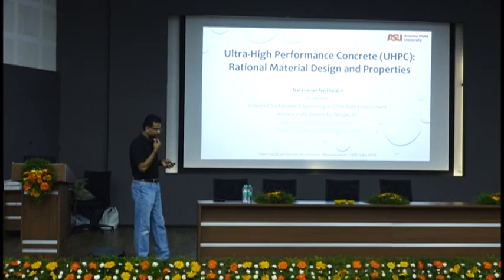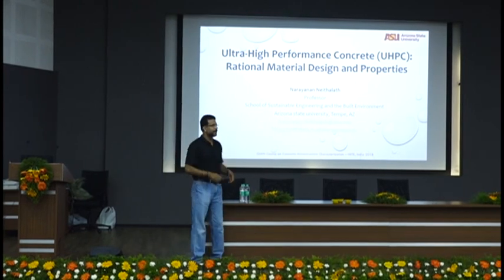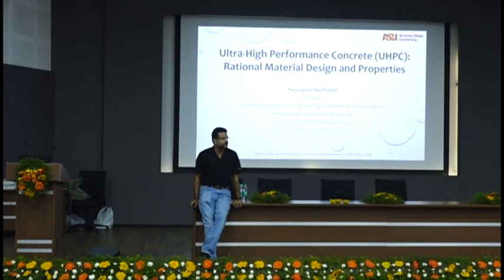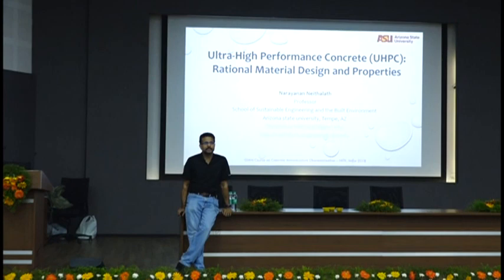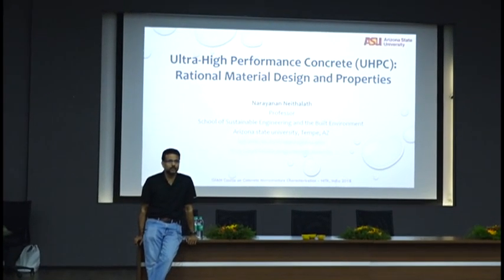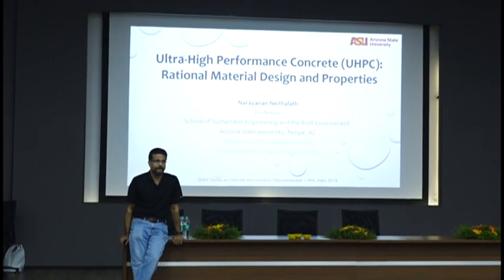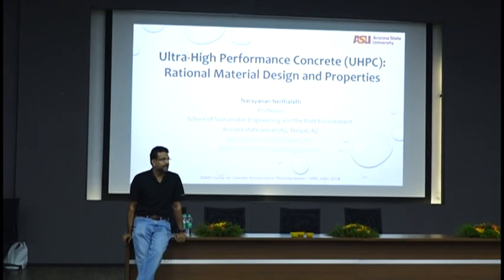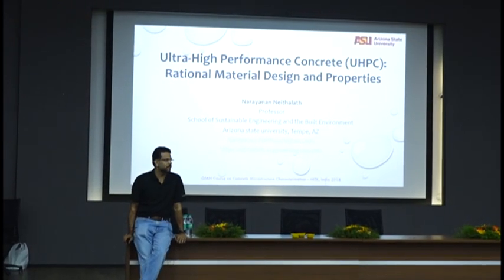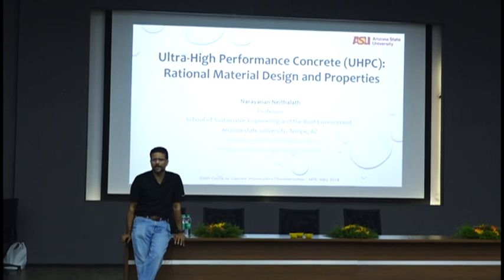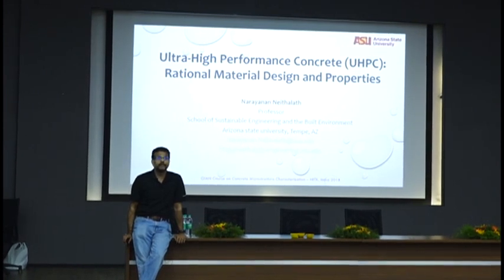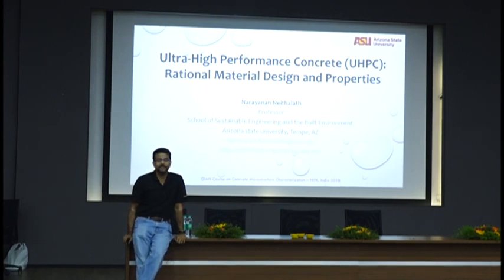Lafarge sells a UHPC called Ductal. You must have heard of that in India. And Ductal costs around $3,000 a cubic yard. Okay, a cubic yard is a little smaller than a cubic meter, about 0.7646 cubic meters. $3,000 a cubic yard, whereas a conventional concrete you can get for $100 a cubic yard. So Ductal charges 30 times more for this ultra high performance concrete proprietary mixture.